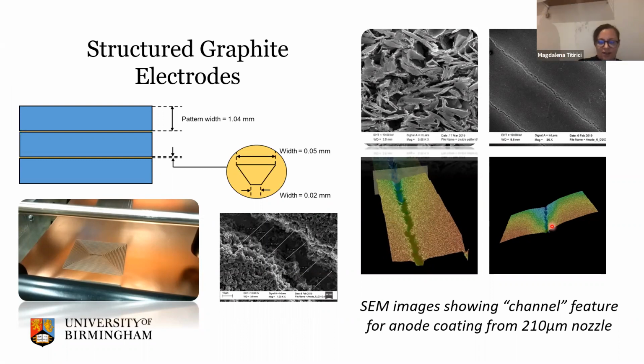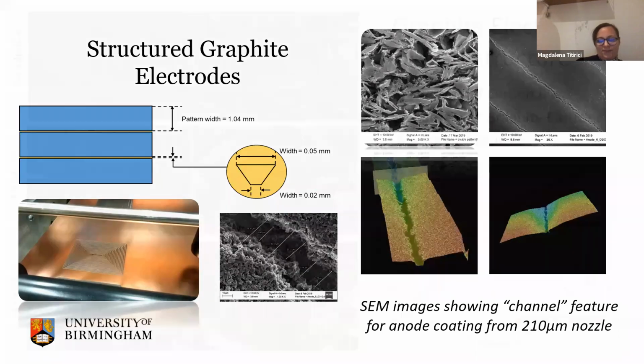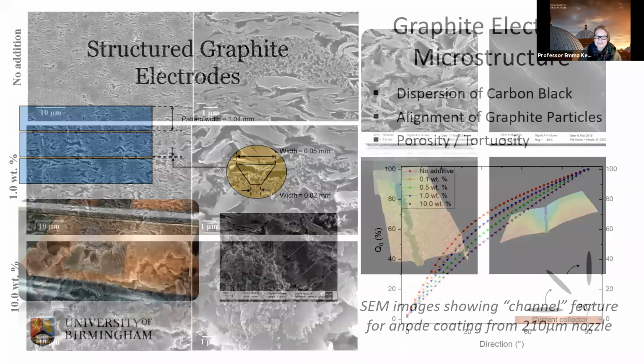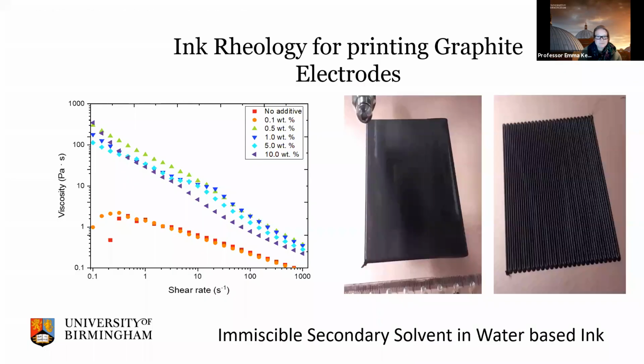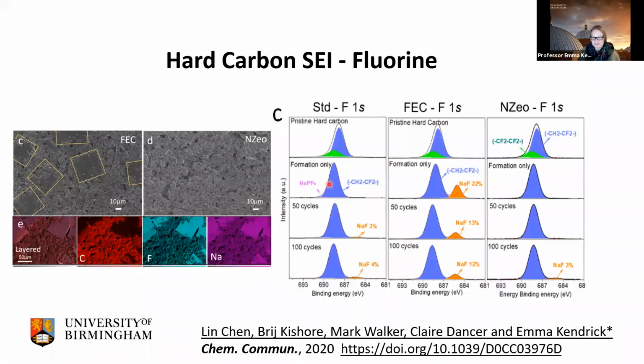So following on the zeolite, Milo is asking if the proposed mechanism of the zeolite addition is that it acts as an in situ water scavenger, avoiding unwanted hydrolysis reaction over time. And then he further asks, does this mean that the benefit has a finite lifetime until the zeolite is saturated? Yeah, I think it probably does matter. Again, degradation happens, you can't stop it. And you can see, we did actually XPS, Mark Walker here at University of Warwick is a bit of an XPS guru, and he helped us enormously with this work. And it wasn't just the sodium fluoride that we saw that was changing in terms of the makeup of the SEI layer. It was also some of the organics on the surface.